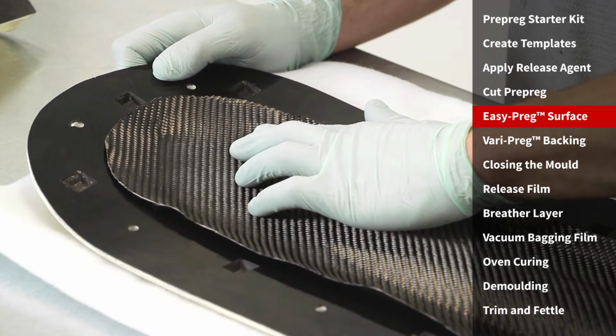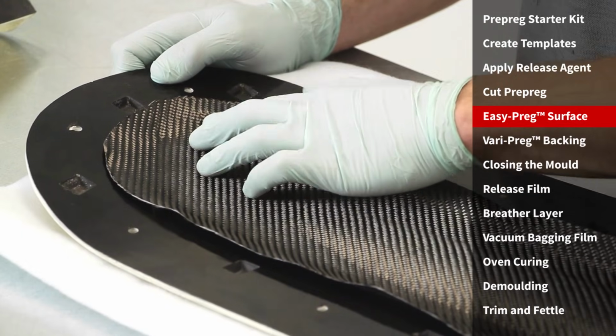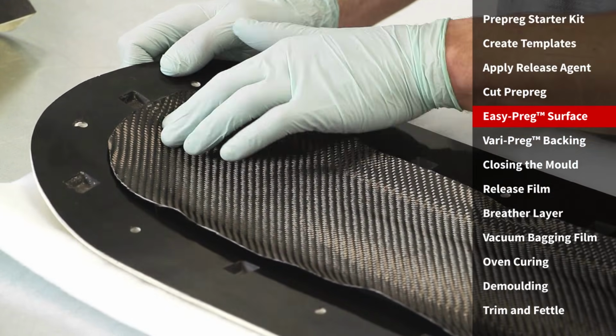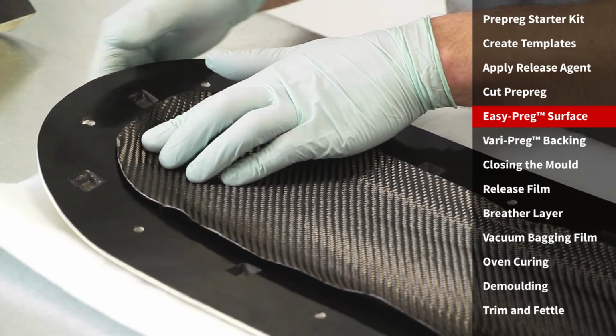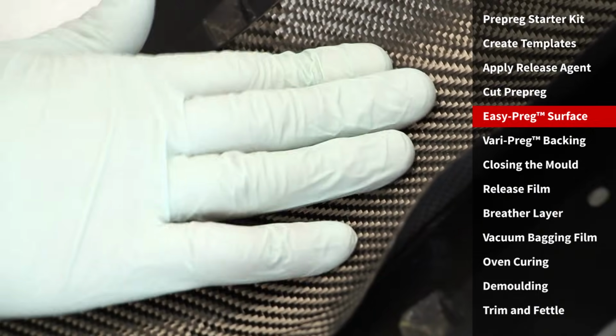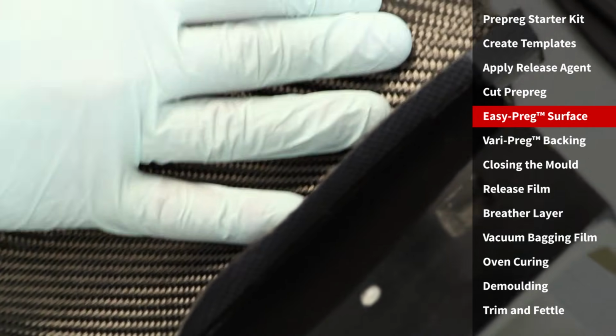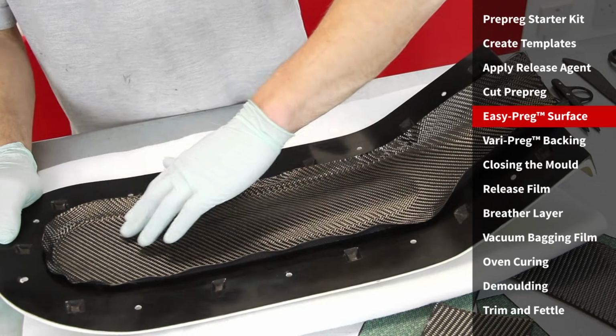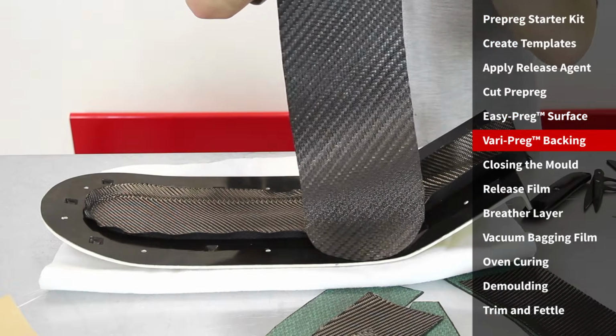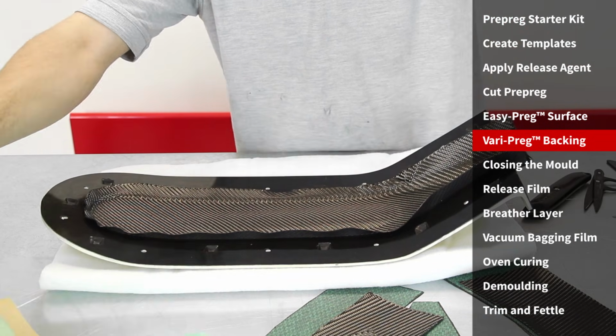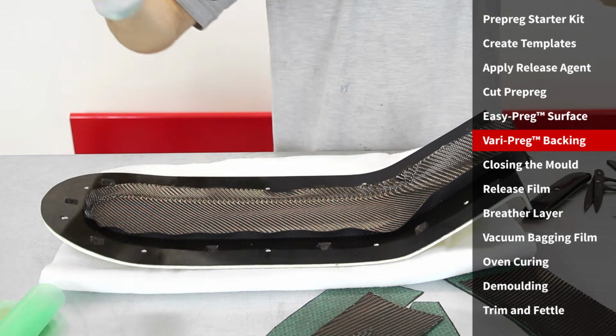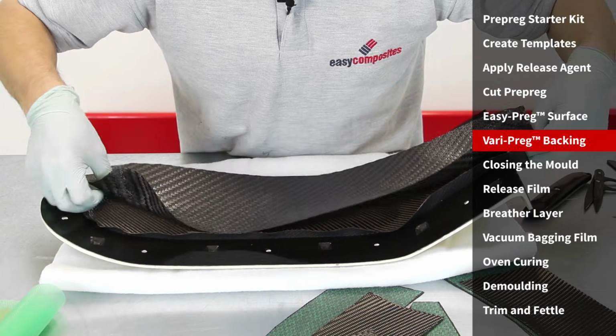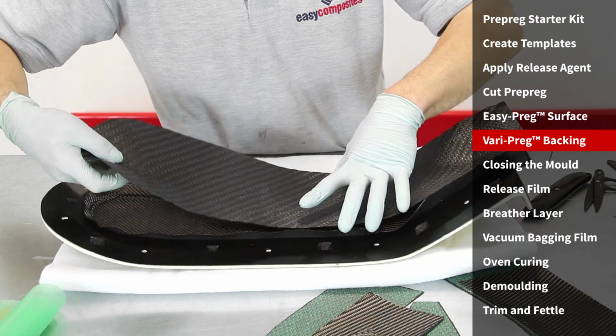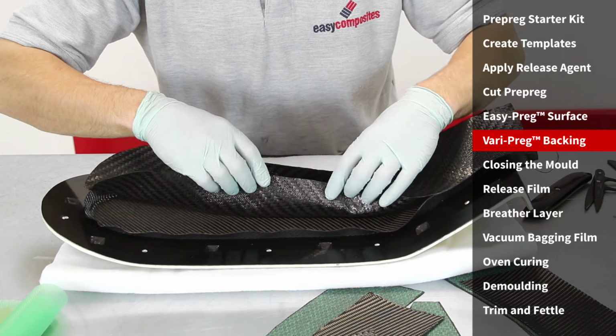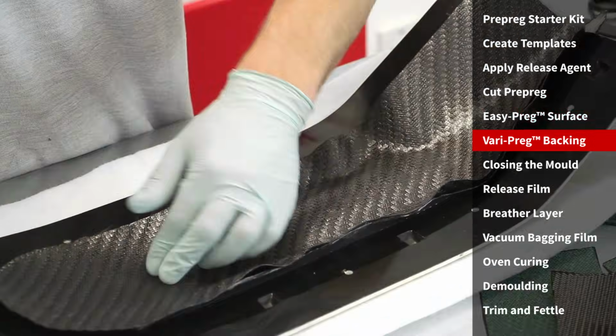In a cooler working environment or for intricate shapes, it's sometimes advantageous to slightly warm the prepreg using a hairdryer or a heat gun to make it tackier and more pliable. In the case of this part, however, it won't be needed. The backing ply is laminated in much the same way as the surface, but extra care must be taken when placing it into the mould, as repositioning can often disturb and lift the surface ply beneath. You will also find that this heavyweight material is less pliable and can take a little more force to manipulate.